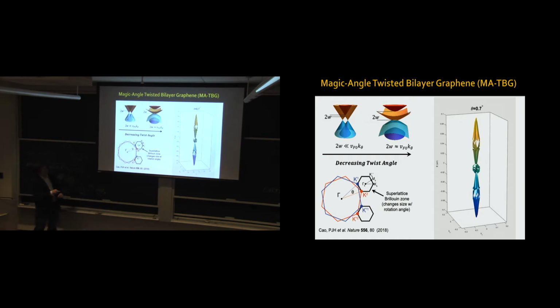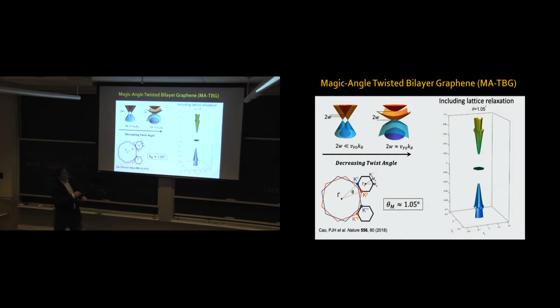Turns out that if you include the lattice relaxation, it's actually a very interesting problem of how these lattices relax to adjust to each other for small angles. If you include lattice relaxation, this magic angle happens to be closer to about 1.05 degrees, although this value keeps evolving as calculations get better and better.